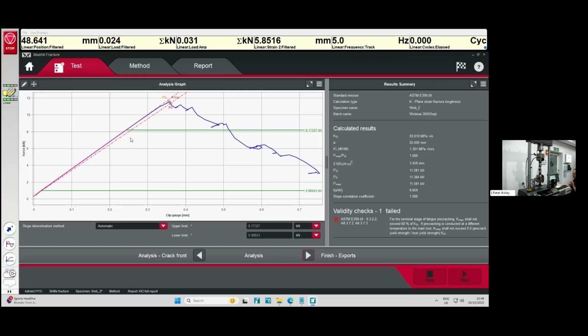Now, what happens if you use the automated fitting algorithm is that you get much better, more reproducible determination. So the scatter in the results was up to 10 times greater from the same data set if you use just visual traditional methods as compared with using this algorithm. Anyway, that's enough about perhaps my hobby horse of reproducible results and repeatable analysis.